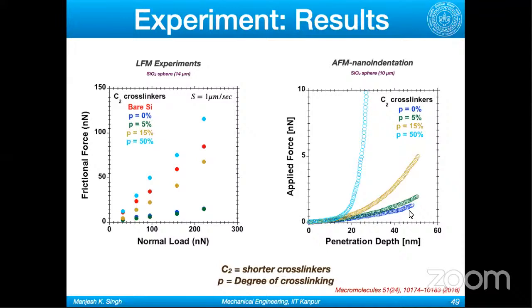And when you have no cross-linking or very low cross-linking, it feels the substrate at a later depth. So it basically tells you that as you increase the degree of cross-linking, the swelling in the polymer gels goes down. And that's why your lubrication, as I said, if you increase the degree of cross-linking, you have no free polymer chains at the outer end, so your lubrication behavior will get worse. But there are studies which show that it will improve your wear property. So you don't want very high friction and low wear, or very low friction and high wear. You want an optimum in between.